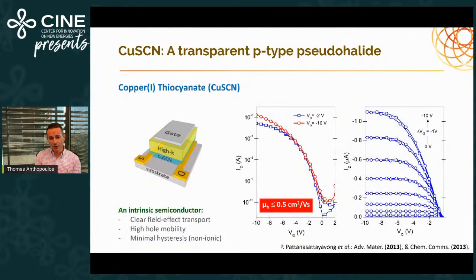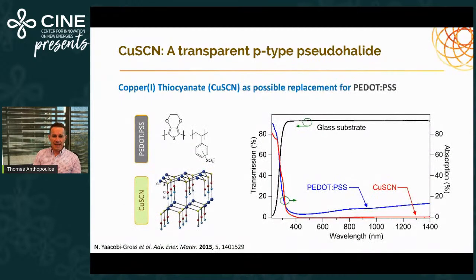So the first data we got that proved that it is actually a p-type semiconductor is transistor data. What we see here is the channel current versus the gate voltage we have used. And we see clear hole accumulation and depletion, which indicates an intrinsic p-type conductivity within that material. Since then, we've been able to analyze, of course, the optical transparency. And the first material we compared copper thiocyanate against was the standard commercially available PEDOT:PSS, which is a standard hole extracting interlayer for most of the OPV technologies and devices found in the literature today.